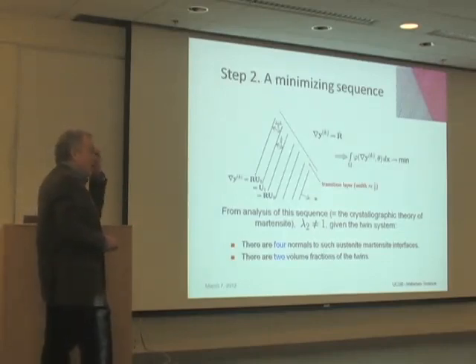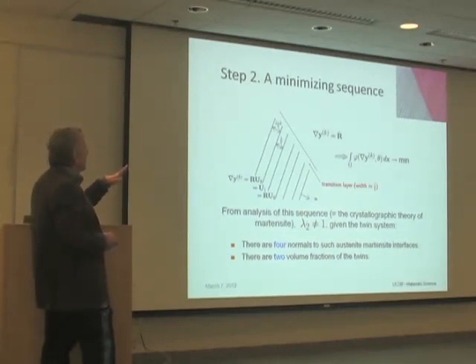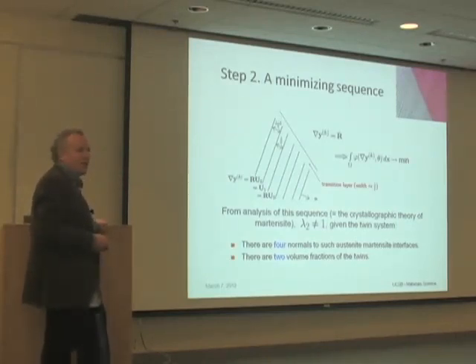The problem is, as I say, there's energy left over in this interface. And we began to theorize, by looking at various cases, that this energy is the main reason for hysteresis in phase transformations. It's not pinning or thermal activation. And it goes like this: